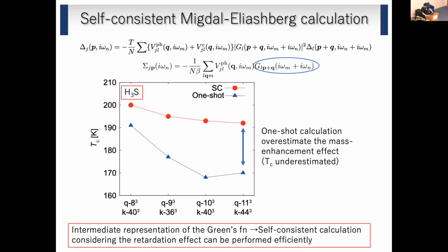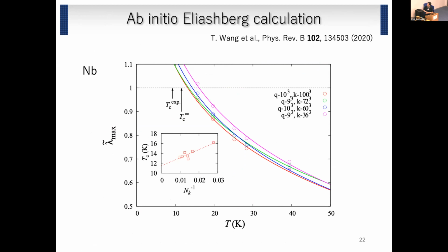But let me mention that this calculation is still expensive for low TC superconductors, because in the case of low TC superconductors, another problem appears, namely, we have to introduce a dense K mesh. And this is a calculation for niobium, and we see that as a function of the number of K points, we still see some deviation, oscillation. And we extrapolated this data and determined TC. But this strategy does not work for a superconductor whose TC is lower than 5 Kelvin, for example. So the calculation of the TC of aluminum is still an extreme challenge.